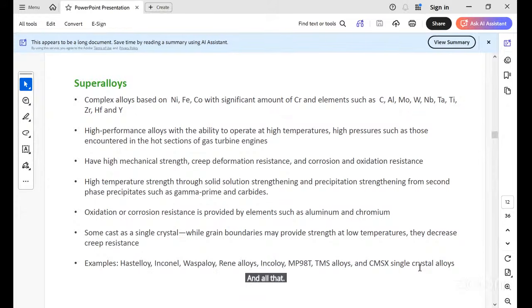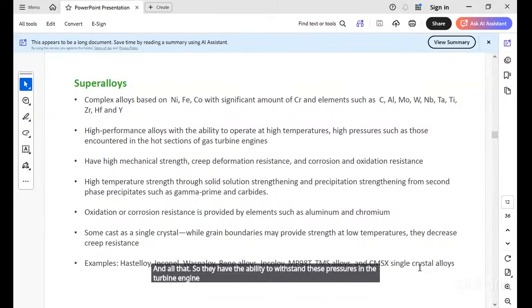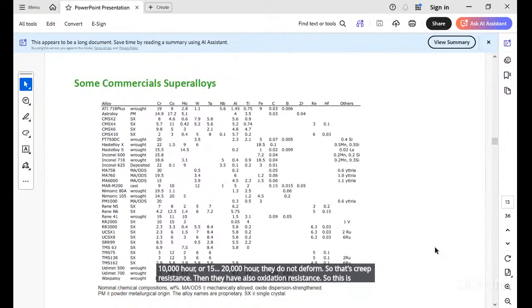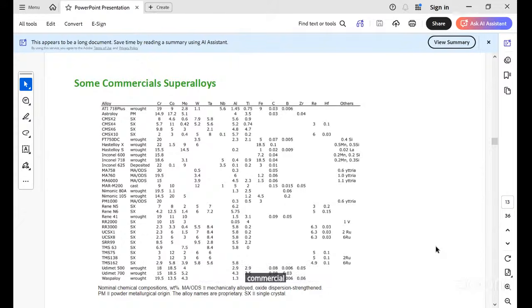They have the ability to withstand these pressures in the turbine engine at 1100 degrees or so. They're very good creep resistant. Over a period like 10,000 hours or 15, 20,000 hours, they do not deform. So that's creep resistance. Then they have also oxidation resistance. This slide I'm not going to spend much time on. It's just for your records, if you want to see some of the commercial superalloys, their chemical compositions are given.